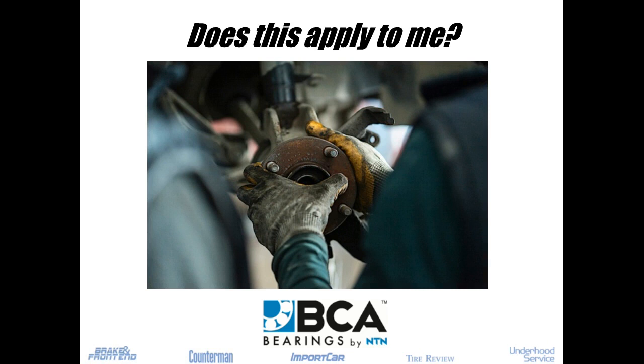Any other ideas? Mark? Well, sometimes also if a bearing is subjected to hitting potholes or hitting a curb at a high rate of speed, it can definitely cause accelerated wear. Upon hitting the curb or the pothole, you're denting the raceway, and now you're potentially introducing contaminant material into the grease, because any dent in the raceway is going to start to get worn down by the balls or the rollers. So it's hard to necessarily determine if it's specifically from an incident where you hit a curb or not.